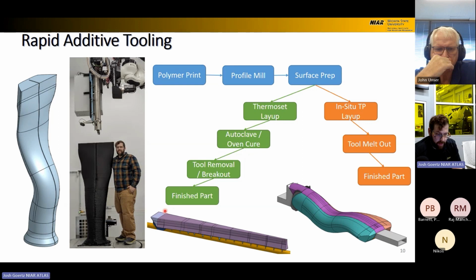So this is a 3D printed spar tool design, which is printed onto a rigid steel mandrel. So you put the mandrel on a horizontal rotator, print the body of the tool with the pellet printing head, profile mill it, and then the tool is something like a carbon fiber reinforced PEI resin, which we can do a 350 cure thermoset on.